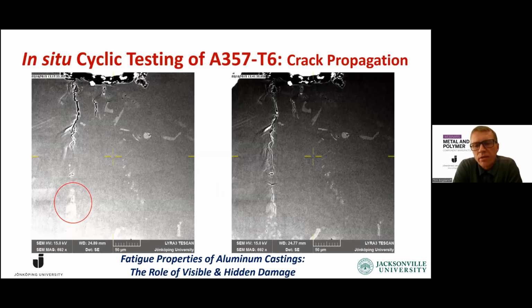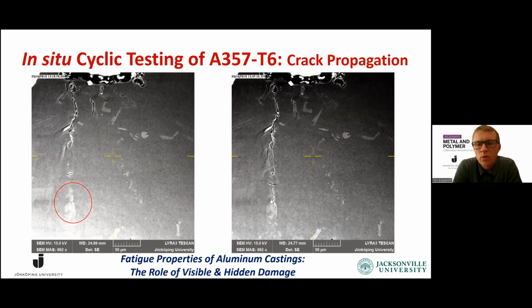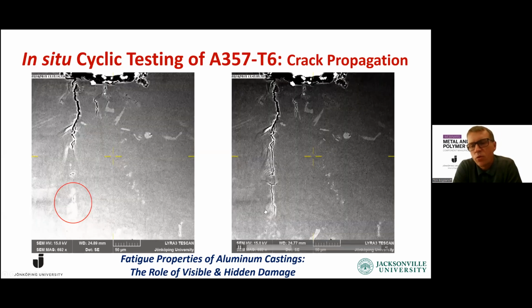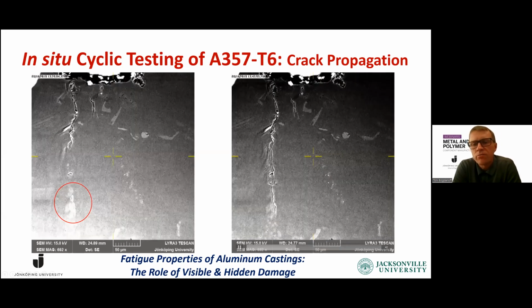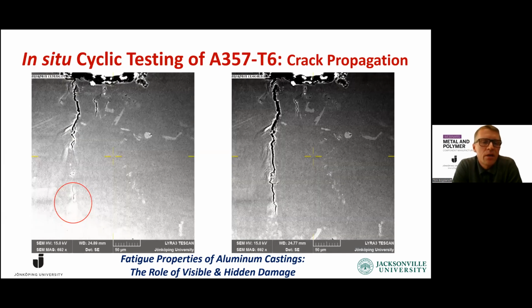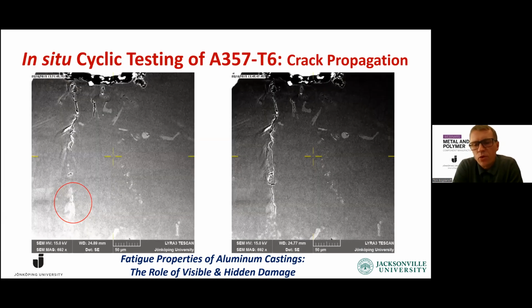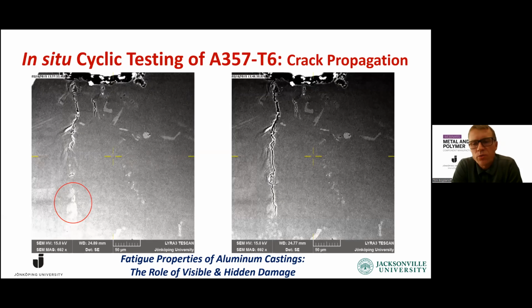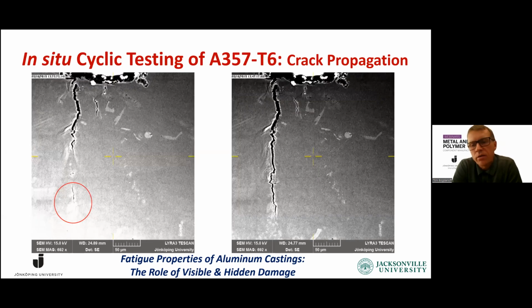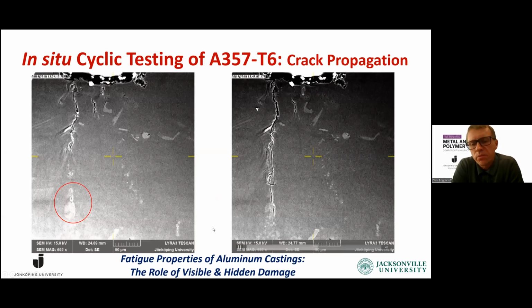that we can see on the right now. It continues to crack until the matrix is deformed until it has a final failure. So we see that this pre-crack that is in front of the highest strain concentration will link together and create the crack path in this case.